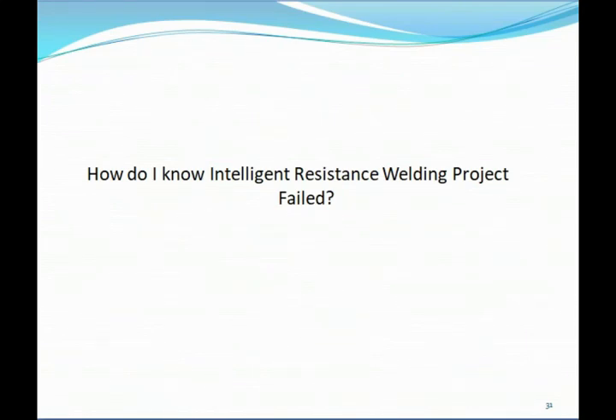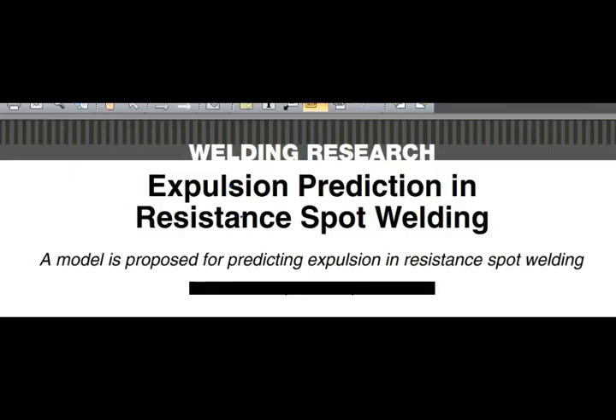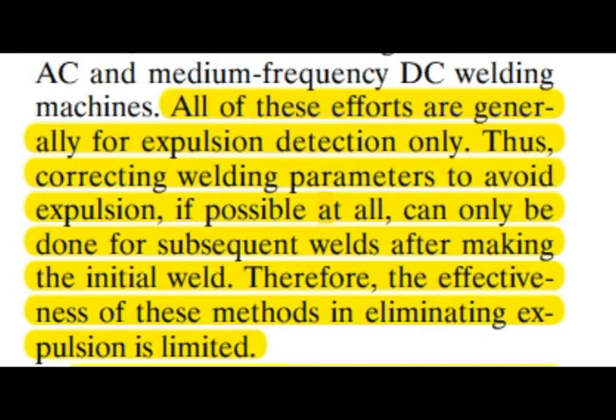The most important clue that they have failed comes from a 2004 paper sponsored by the consortium. "All of these efforts are generally for expulsion detection only. Thus, correcting welding parameters to avoid expulsion, if possible at all, can only be done for subsequent welds after making the initial weld. Therefore, the effectiveness of these methods in eliminating expulsion is limited." What they were really saying is, we started trying to correct welding parameters to avoid expulsion, but we found out we don't know how to do it, so we have to scale back to monitoring.